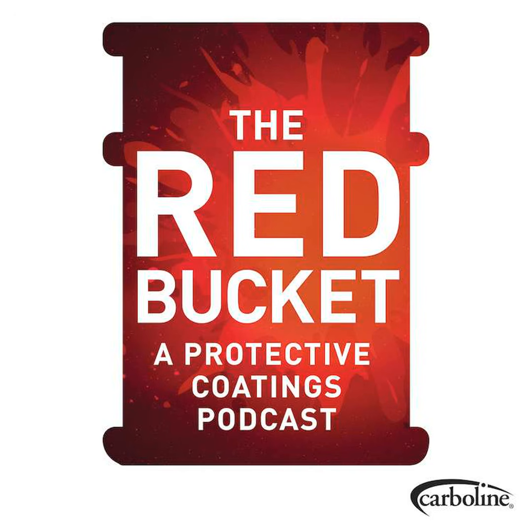Well, let's talk about the whole system. First of all, most of these materials, including ours, are water-based. So it is a very good idea, and we always recommend putting a primer on the substrate first. Not very picky of what type of primers: epoxy, modified epoxies, just about anything can be used as long as it creates a barrier coat. If you apply a standard water-based coating directly to carbon steel, you'll have what's called flash rusting. It'll almost look like freckles that bleed through the coating. So let's get the prep done.